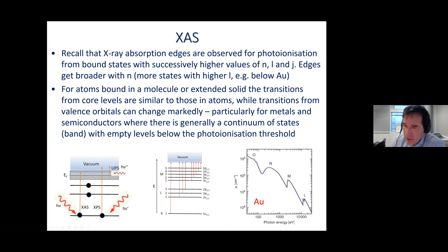And that reflects the fact that the core electrons are very tightly bound, and they're almost completely insensitive to the chemical binding or the chemical character of the element. As you go to less and less tightly bound electrons, those higher energy electron states become more implicated in the binding. And instead of seeing sharp states, you start to see shifts, states whose energy is tuned somewhat through entering into chemical binding with the things around them. And in the case of metals, for those of you who are familiar with metallic energy levels, the valence states, or the least tightly bound states, actually are no longer discrete energy states. There's a whole continuum or a band of energy.